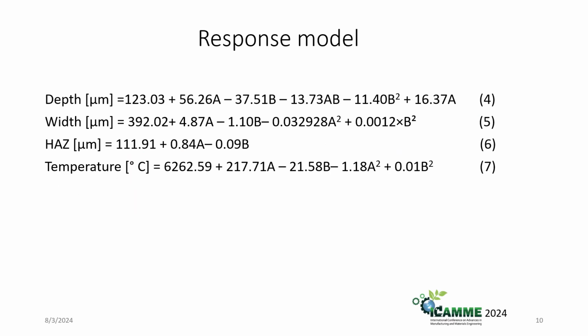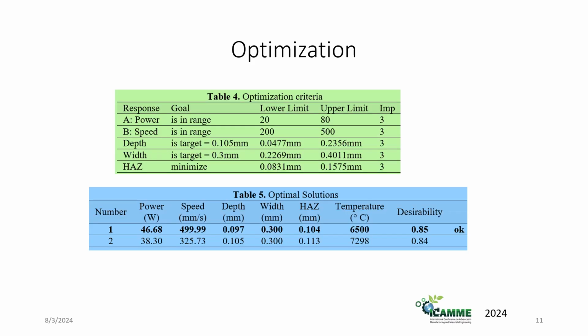The response model was developed, shown in this slide. Depth, width, and temperature show a quadratic relation, while the heat affected zone shows a linear relation. Then optimization was carried out in order to get a channel having a depth of 105 micrometer and a width of 300 micrometer, with the aim of having minimum heat affected zone within the range of power and speed. The optimization was carried out under numerical optimization of RSM software. The optimal result is shown in table 5.